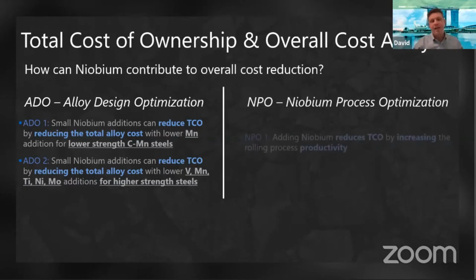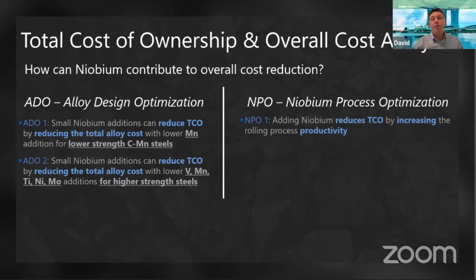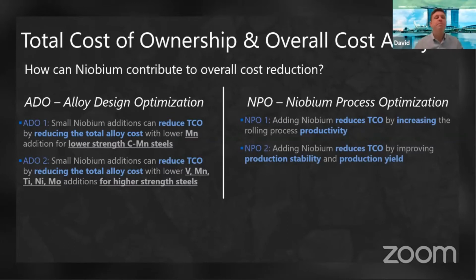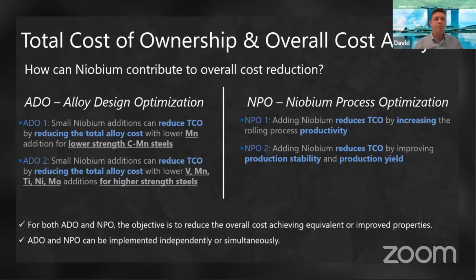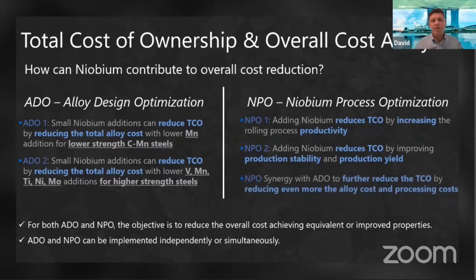On the processing side, we like to use niobium to increase productivity and also production stability, which can be achieved by a better balance of the strengthening mechanisms, leading to higher production yield. In both cases, the alloy design optimization or the niobium process optimization, the objective is to reduce the overall cost by achieving equivalent or improved properties at a lower cost. So all the presentations and everything that I'm going to show in these slides and cases are all cases where we achieve equivalent or even improved properties, which is usually true for toughness and ductility related properties. Alloy design and process design optimization can be implemented independently or simultaneously. And in many cases, what we could see was a synergy between both process and alloy design optimization, bringing even further cost reduction or productivity increase or improved yield.